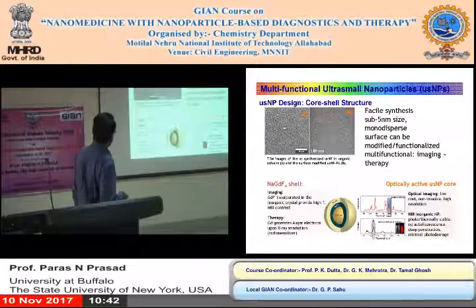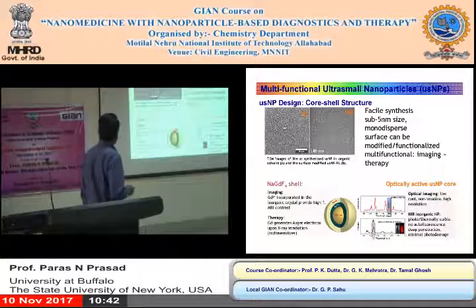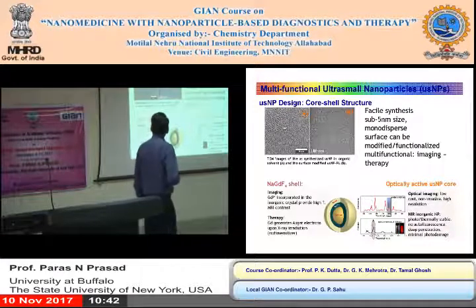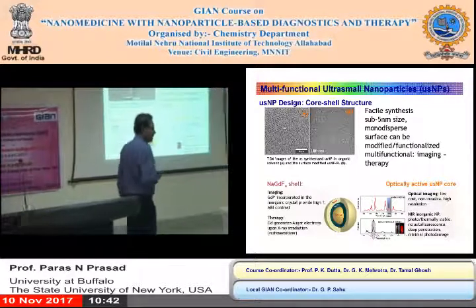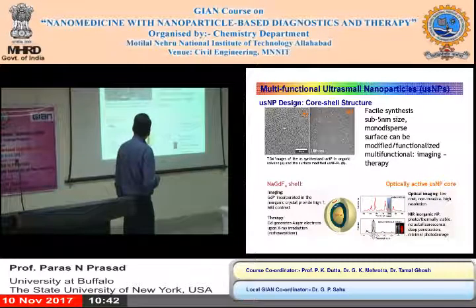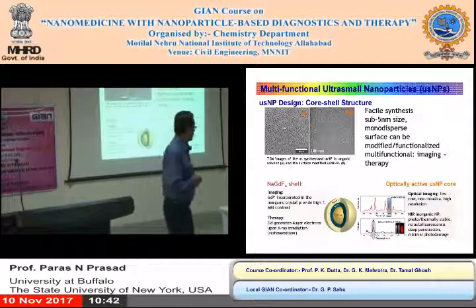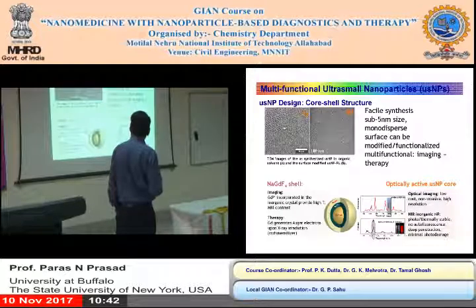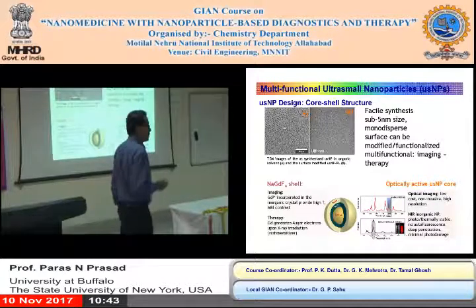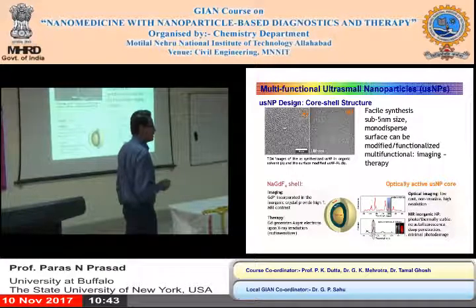And here the idea is that you can have a core of sodium yttrium fluoride doped with either an emitter or upconverter for photodynamic therapy to convert light, and there is another therapy that I'll tell you about later. And then you have a shell that contains gadolinium, and gadolinium can be used for MRI contrast.